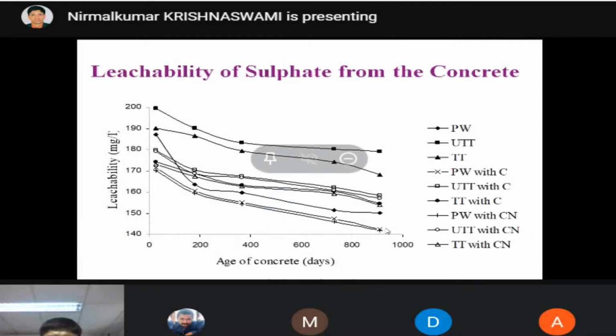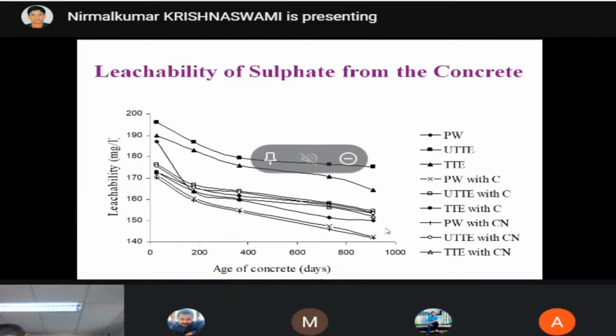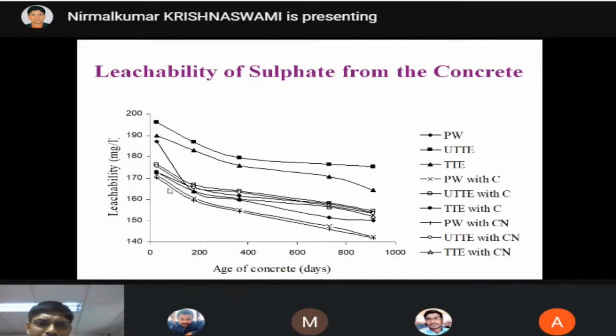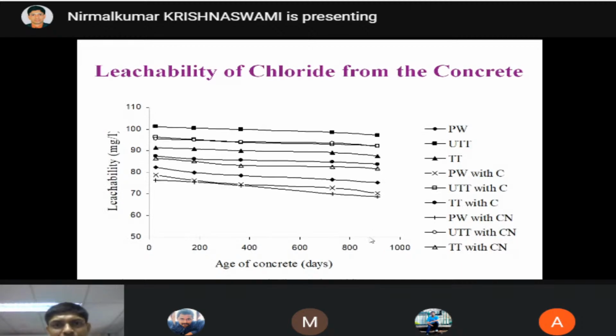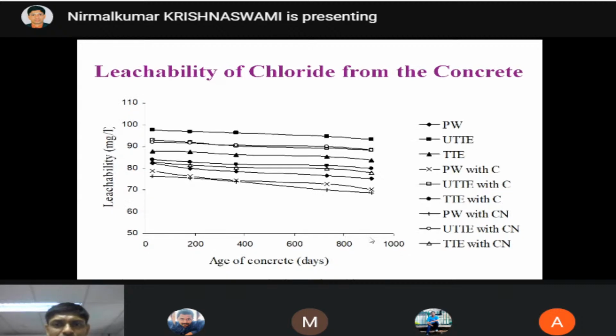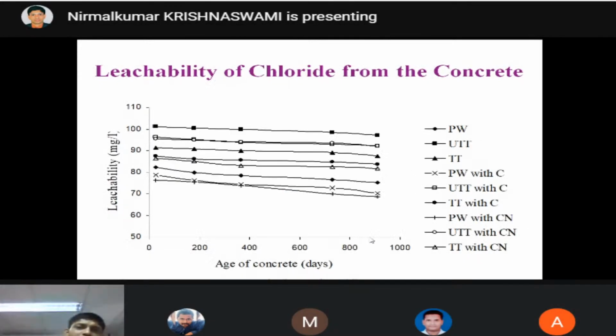This is for sulfate attack for concrete with tannery effluent. This is for textile effluent, the concrete constructed using the textile effluent. Here also, when we add the admixture, it is less than 180 milligram per liter, and it is getting reduced as the age passes. Then this is leachability of chloride from the concrete. This is for tannery effluent and this is for textile effluent. I have determined the leachability for both sulfate and chloride.